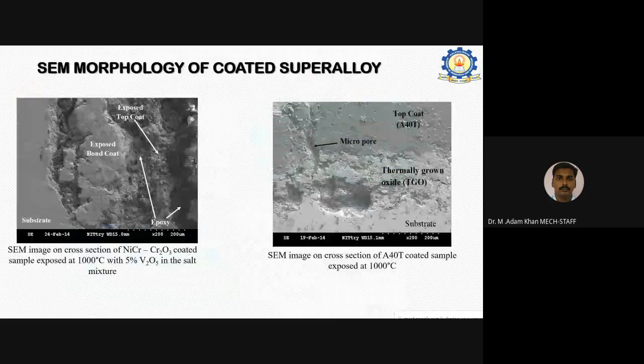So this is the cross section. This is the substrate. This is the nickel chromium bond coat, and this is called the top coat. The other things are epoxy. At the same time, you can see this is alumina titania, so this is ceramic as usual. The ceramic has micropores inside to make a TGO. This is called the substrate. This level is called the TGO.